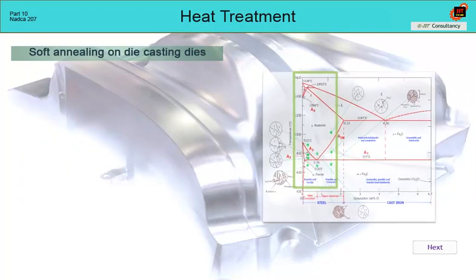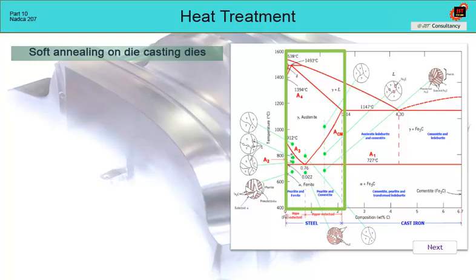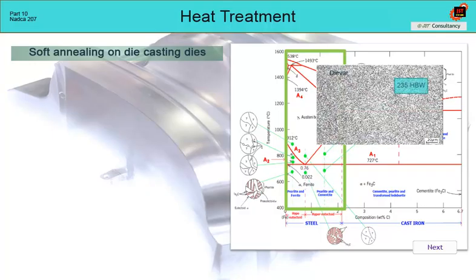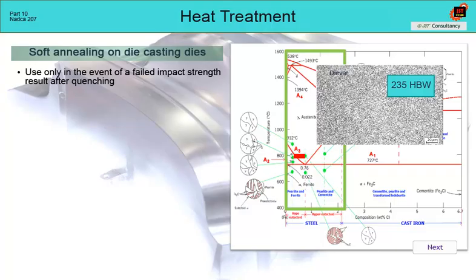Soft annealing is used very rarely in the NADCA 207 system. Normally, this is the condition of steel that is purchased with a maximum hardness of 235 Brinell. However, if the impact test after hardening is not okay, the heat treater must anneal the die to a soft condition, and just after that can repeat the hardening.